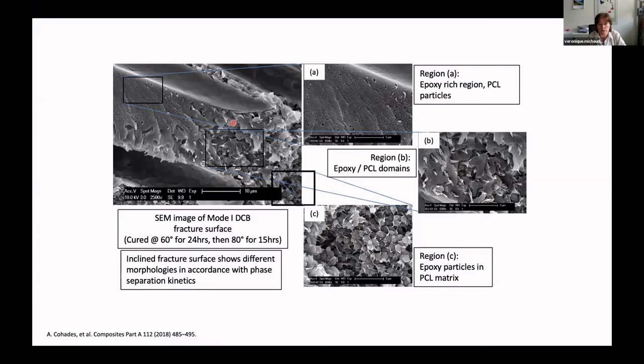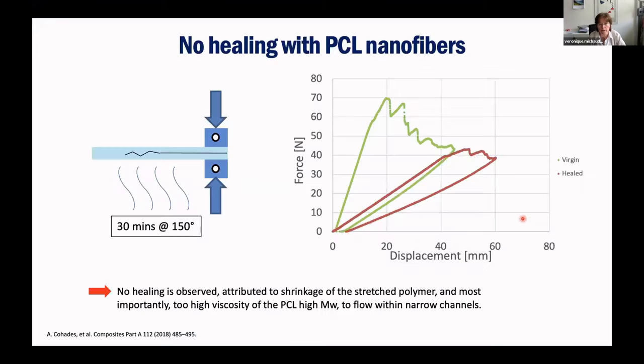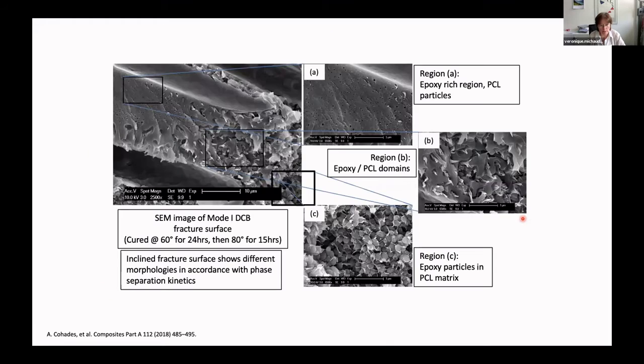So we see that we have different days, but we do have this phase separation kinetics taking place when we cure at 60 degrees and then 80 degrees for 15 hours to do the post-cure. So this is perfect and it works well. And we actually published all this also, this is in 2018.